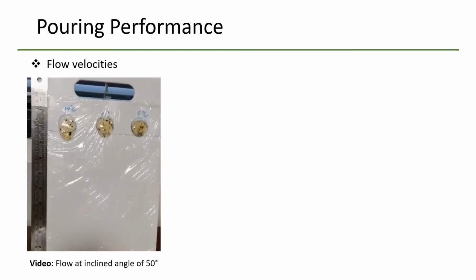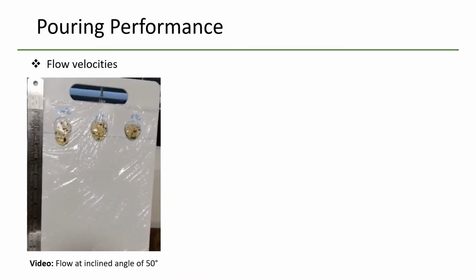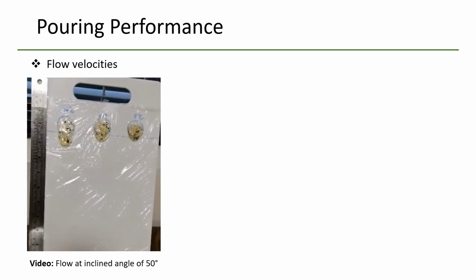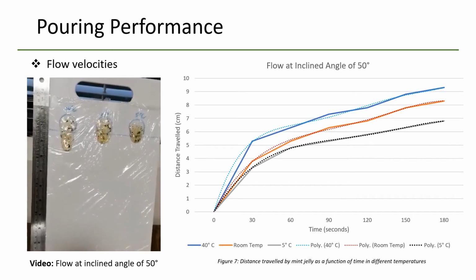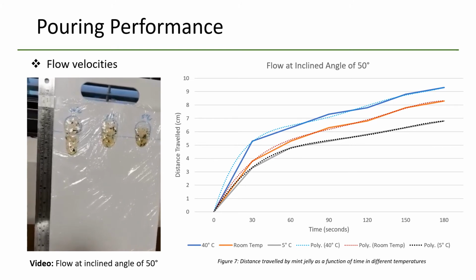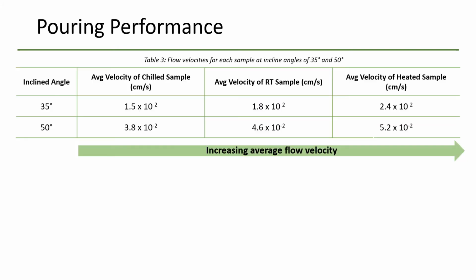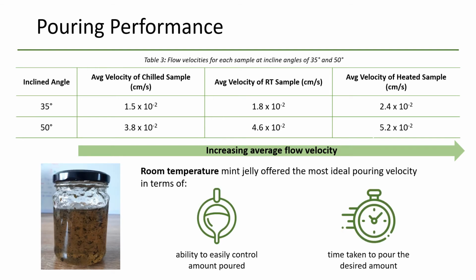Pouring performance can also be evaluated by comparing flow velocities. 4 grams of each temperature sample were placed on the board and tilted at angles of 35 degrees and 50 degrees. A distance versus time graph was plotted to estimate the average flow velocities. For both angles, the heated mint jelly had the fastest velocity, followed by the room temperature, and lastly the chilled. This can again be explained by differences in the viscosity of each sample. In terms of product performance, the room temperature had the ideal flow velocity, where flow is slow enough to pour in a controlled manner, yet fast enough that it wouldn't take too long to pour the desired amount.